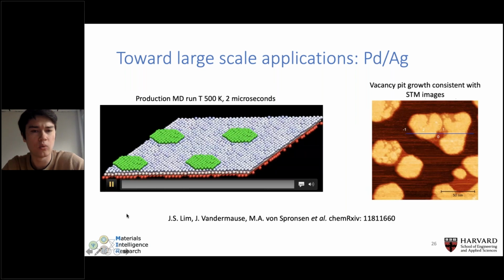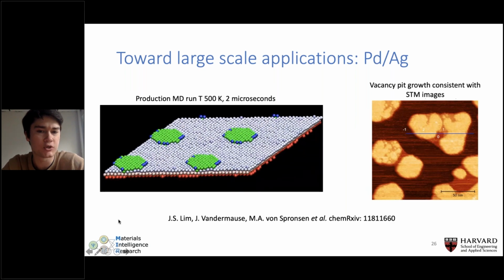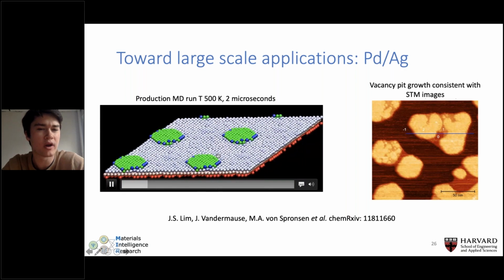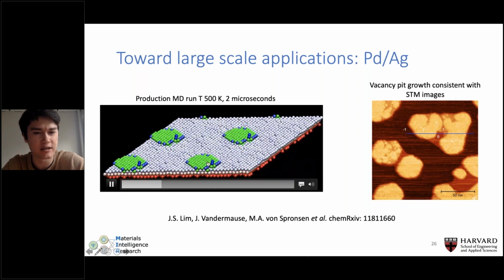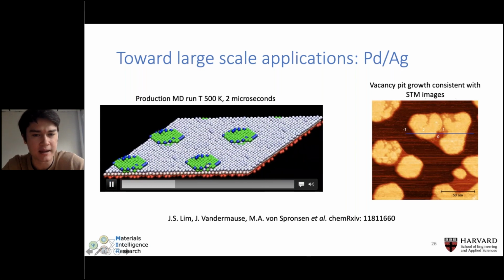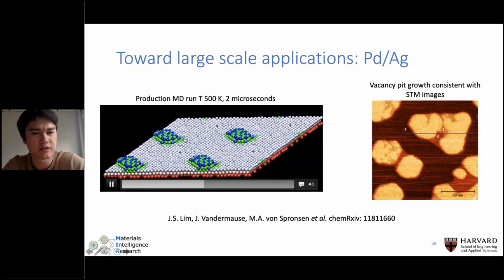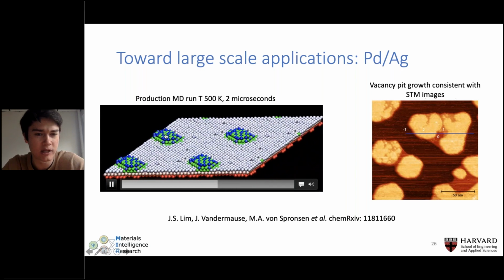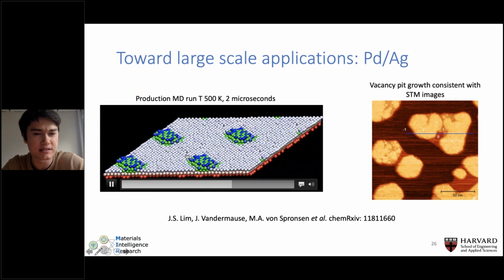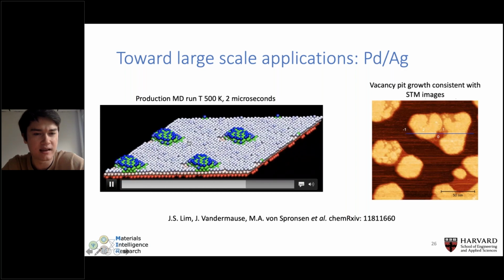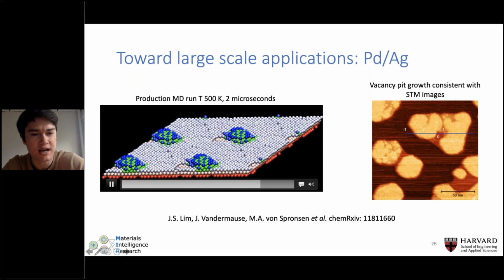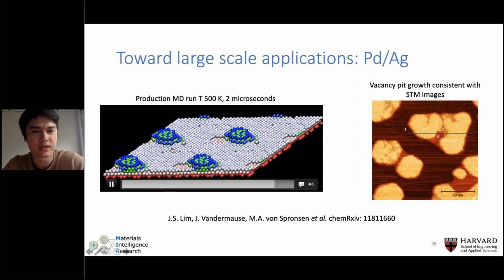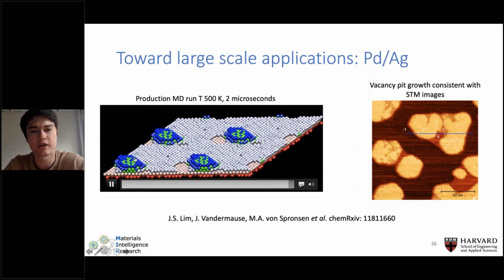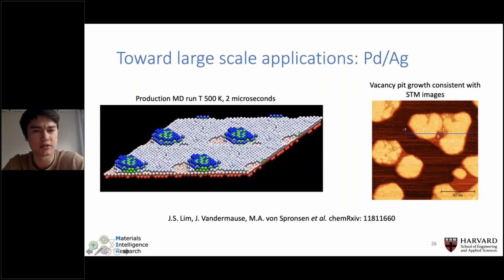And what we did with the final model was we applied it to microsecond timescales to see what are the restructuring mechanisms of this palladium island as a function of time. And you can see sort of non-trivial, interesting behavior happening here where silver atoms climb on top of the island slowly over time. And that introduces these vacancies in the silver surface that grow over time and form vacancy pits. And those vacancy pits move around and they combine with each other. And it's this kind of non-trivial phenomenology that's emerging at the microsecond timescale.